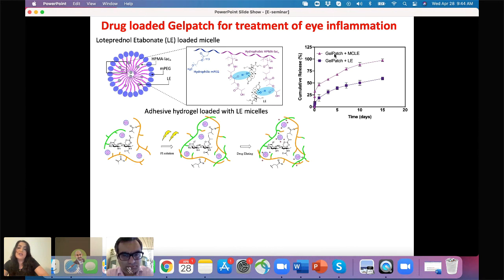On the top, you see gel patch combined with micelles loaded with LE, and then we observe complete release of drug, 100%, over 2 weeks. This is the profile that we want for the treatment of inflammation in the eye. But if we put free drug inside gel patch, we also have control release of the drug, but we cannot achieve 100% release over time.